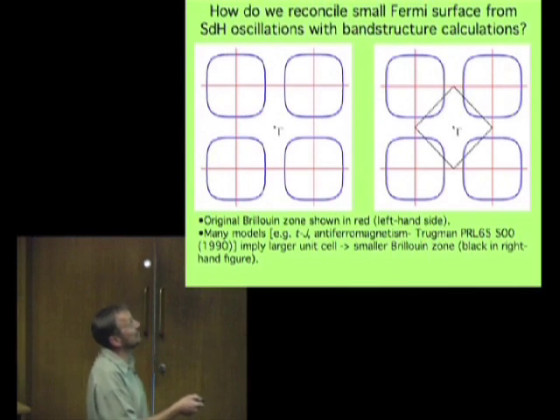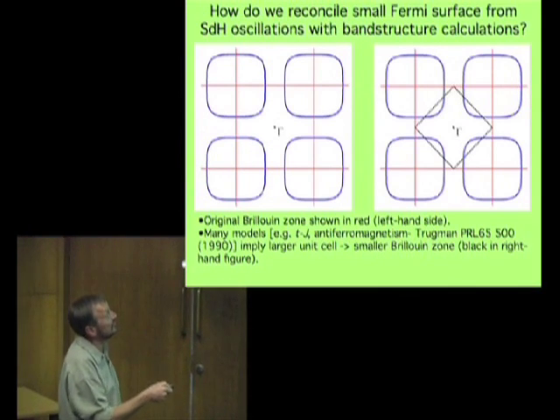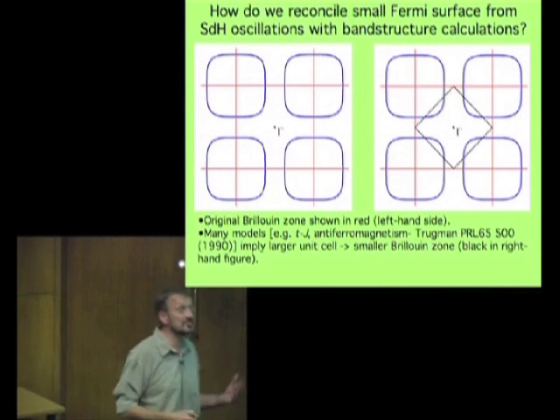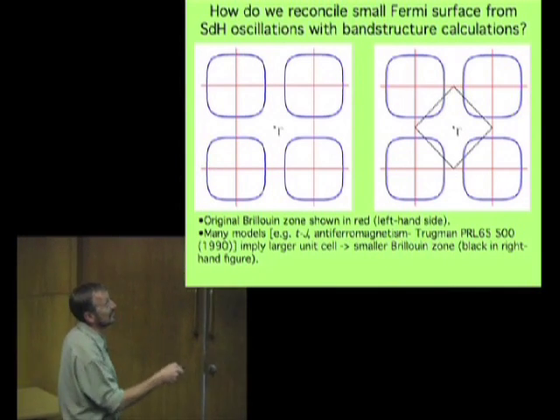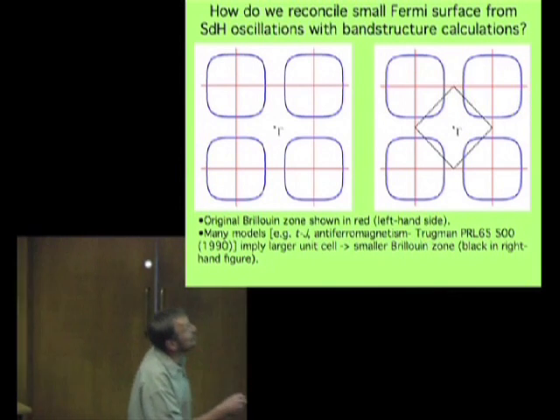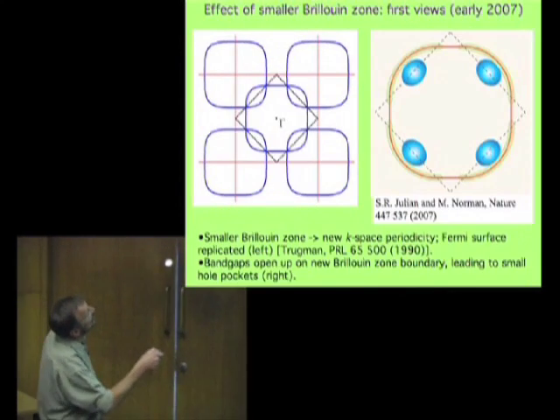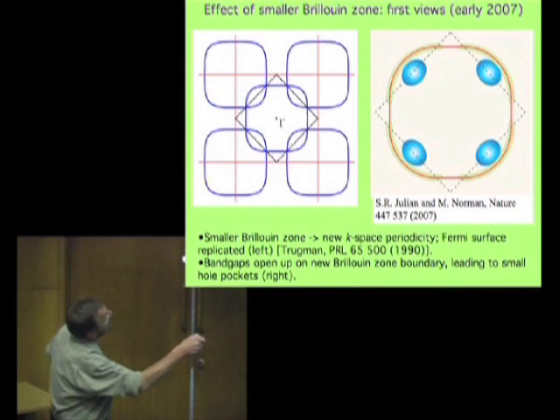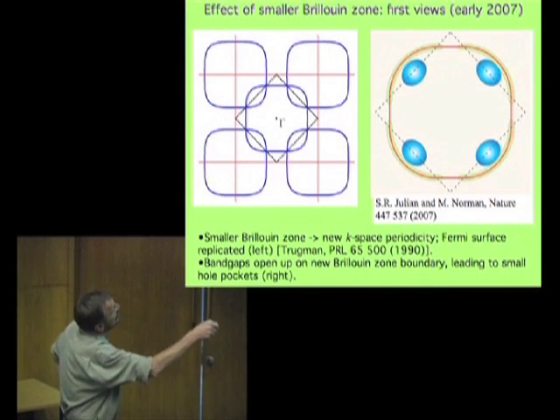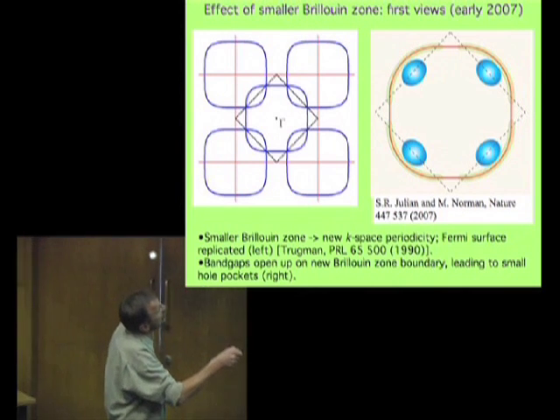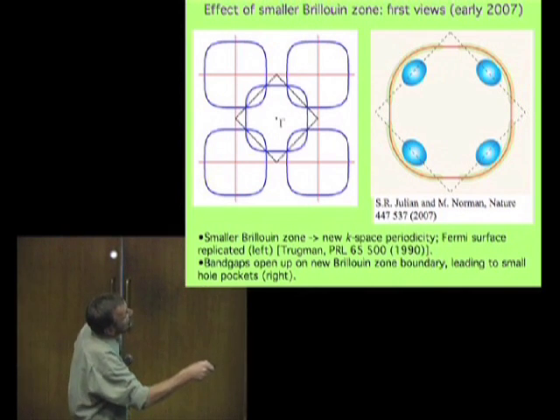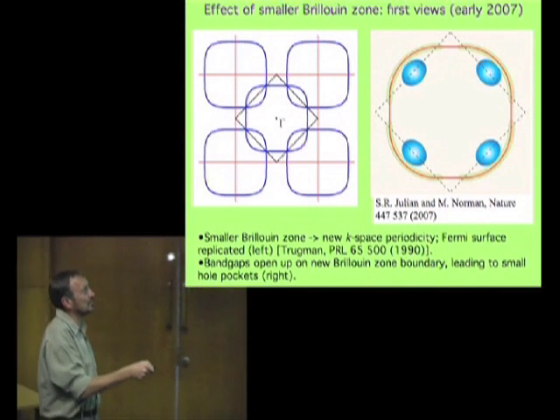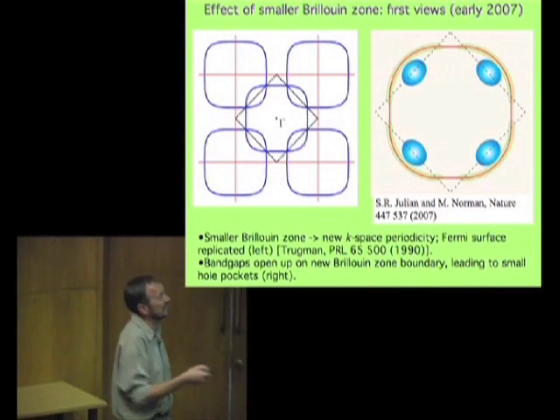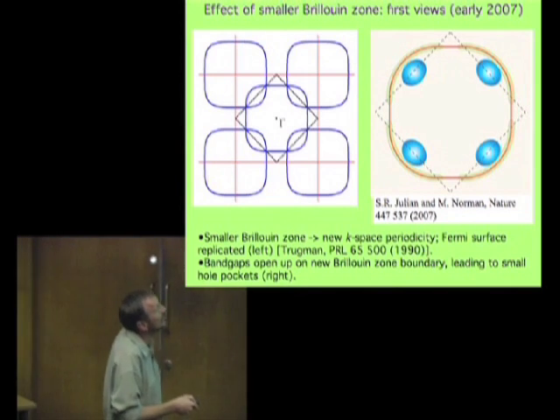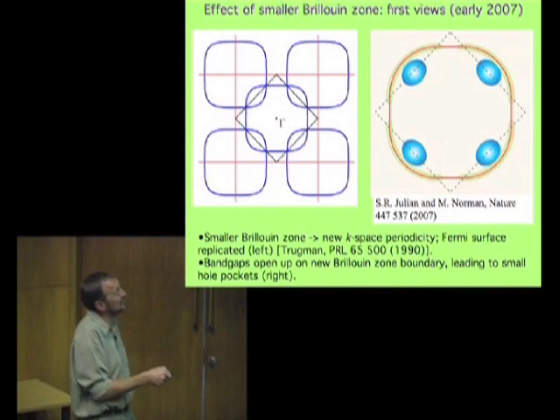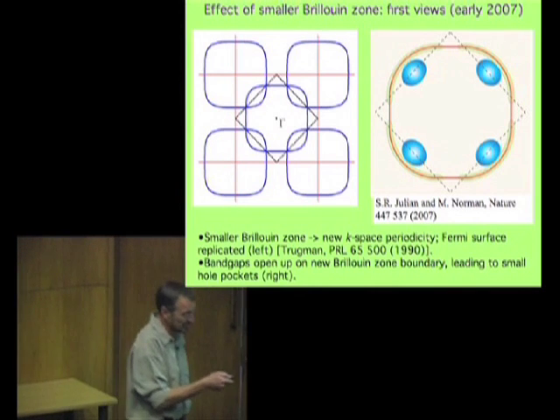So what was happening in the cuprates? Well, let's suppose that you have some sort of distortion. The distortion need not be structural, it can be magnetic, like an antiferromagnetism, and we get this new Brillouin zone. Well, we get gaps opening along the Brillouin zone boundary. We have a replication of this part of the Fermi surface in here, and these gaps and this replication result in little Fermi surface pockets like this. And this was a proposal by Steve Julian and Mike Norman after the first measurements were published in the middle of last year. So we have little pieces of Fermi surface due to the antiferromagnetism introducing a new periodicity into the system.